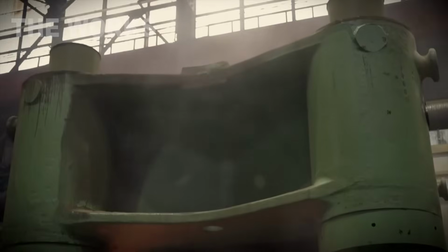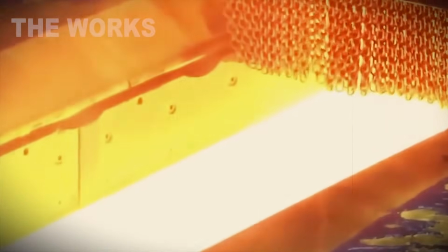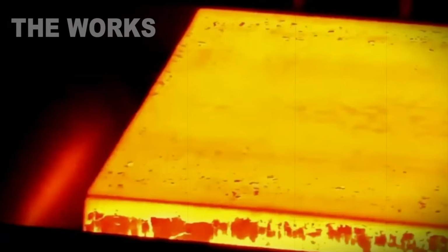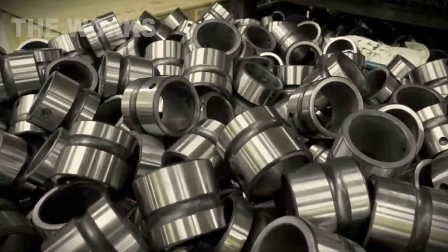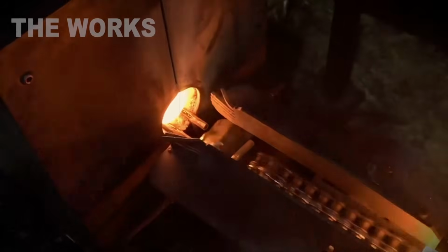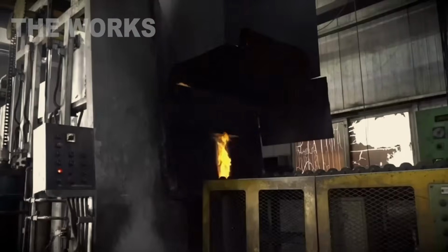Blanks are heated to 1,560 degrees. Stamped into rings on a press generating 1,200 tons of force. You get a ring with an outer diameter of 4 inches. Inner diameter, 3.1 inches. Height, 0.8 inches. Rings undergo heat treatment.